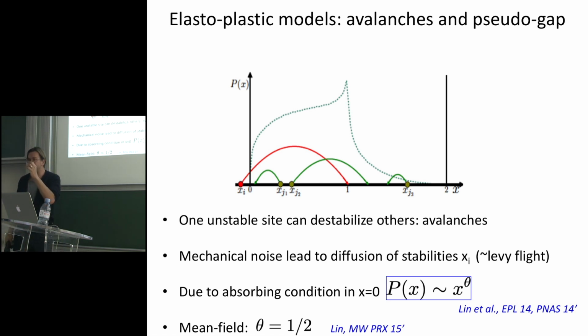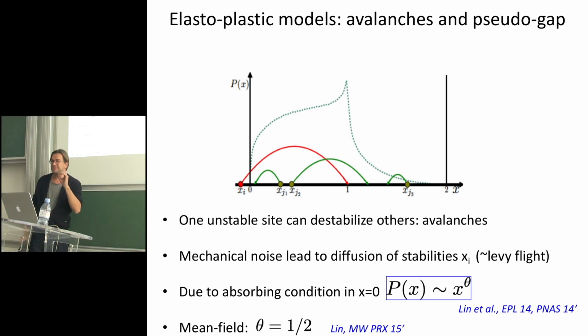And the physical reason is not too complicated. It comes from the fact that those sites, due to mechanical noise of guys failing, do some kind of random walk. But for them, this is an absorbing condition. If you had a random walk with an absorbing condition, you know that the concentration will vanish linearly close to this point. Here it's a bit more interesting because it's not really a random walk. The noise, I told you, can have big kicks and small kicks. Actually, if you forget spatial correlation, then the model becomes essentially a Levy flight. So the mechanical noise is much better described by a Levy flight, which has a few big jumps and very small ones.